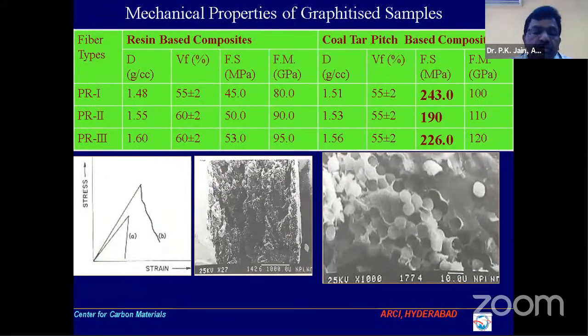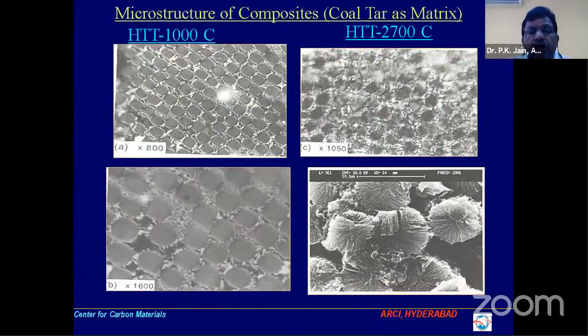But when we graphitized this sample, the situation changed, and the fiber matrix interface was modified, and PR3, which has a higher surface group, has given a very reasonable increase in these properties. But the highest was 243. Now this is comparable to the T300. So that has given a very strong reason that if you just do the processing in a controlled way, one can achieve good properties with a low cost material. This is the microstructure under polarized light, one can see the anisotropy, and during this graphitization process, the fibers also get modified.